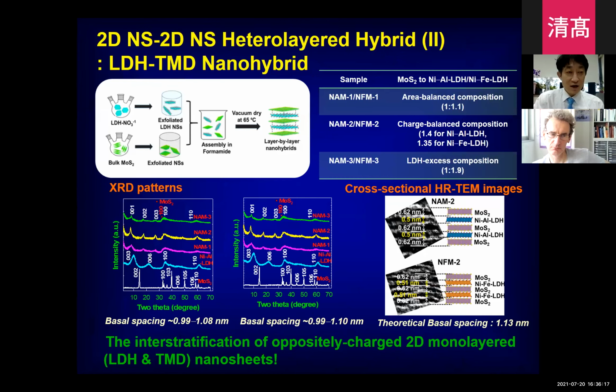This is another type of 2D system. Even though molybdenum sulfide is neutral, as I told you in the introduction section, during the chemical exfoliation process, we intercalate lithium ions into the molybdenum sulfide lattice. So it induced the partial reduction of the molybdenum sulfide. As a result, the exfoliated molybdenum sulfide nanosheets are negatively charged. So we can easily apply those materials as a building block.